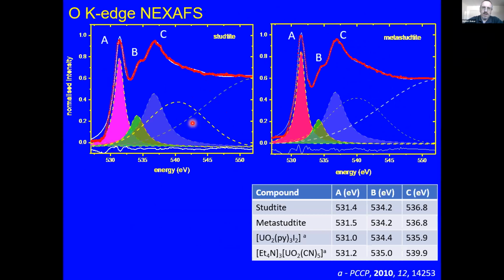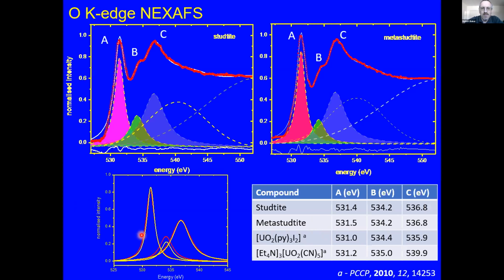So if we look at this with a bit of eye of faith, you can see that there are 3 transitions in studtite and metastudtite, and curve fitting for these, we get positions A, B, and C, which don't really change very much compared to the 2 of them. And they're pretty close to examples in the literature of well-defined species as well. So this was rather disappointing, but when we overlaid the fitted peaks, what we see is that this transition here is much broader in the metastudtites compared to the studtite. And this is something that was also observed in these 2 complexes as well.